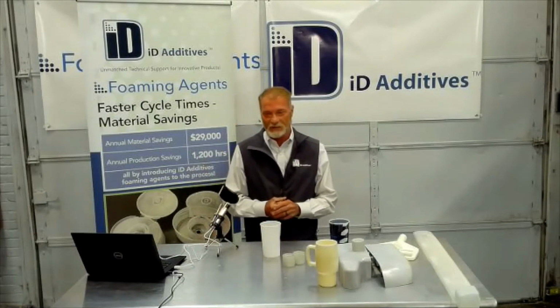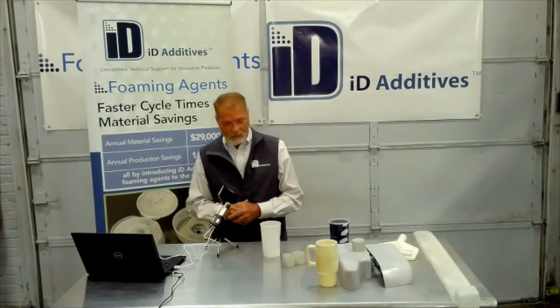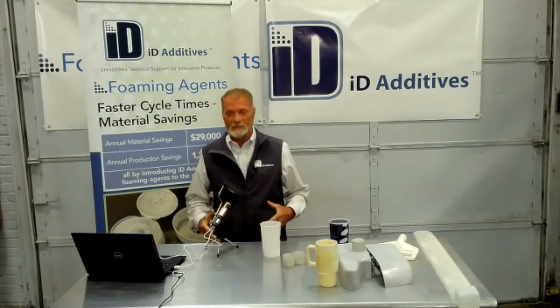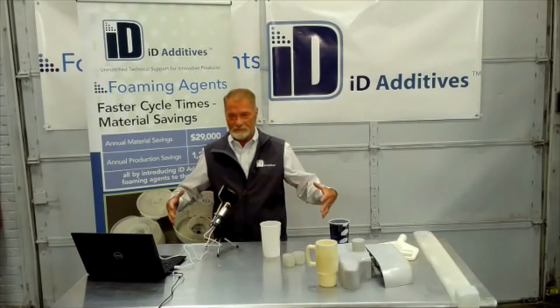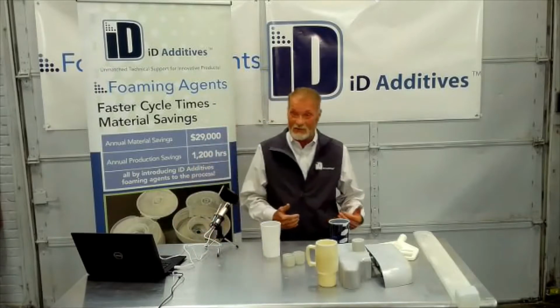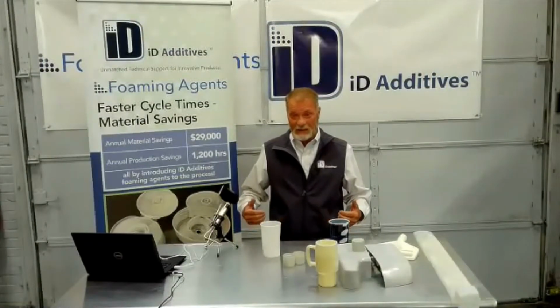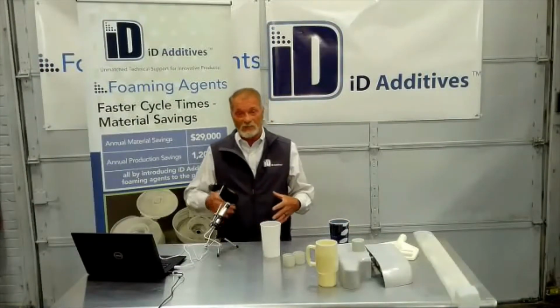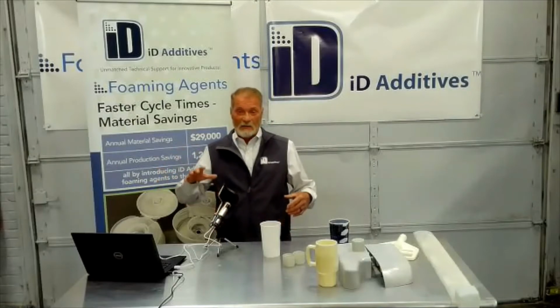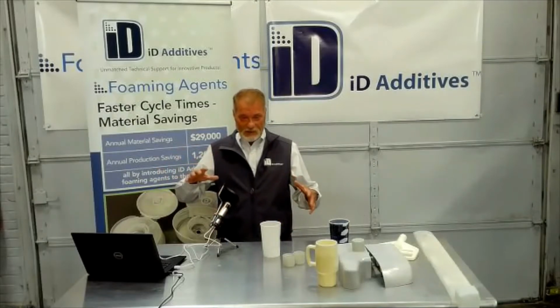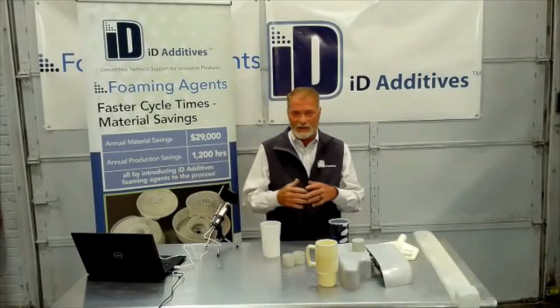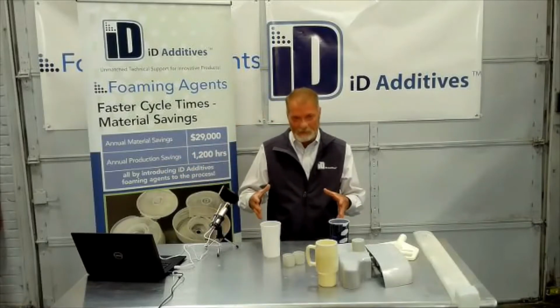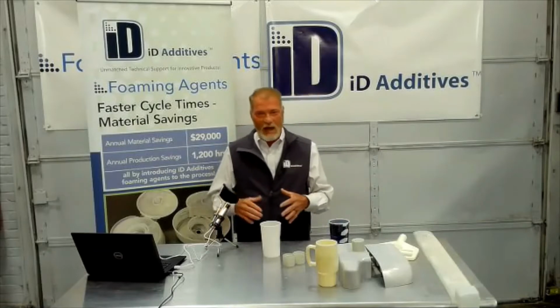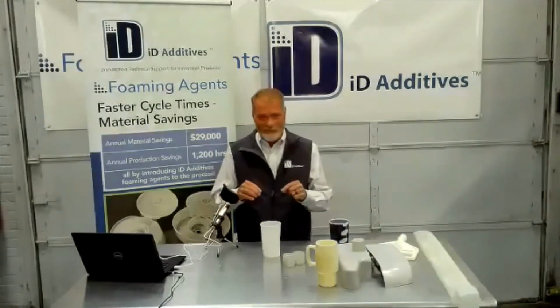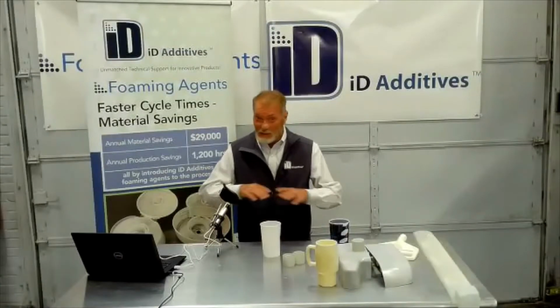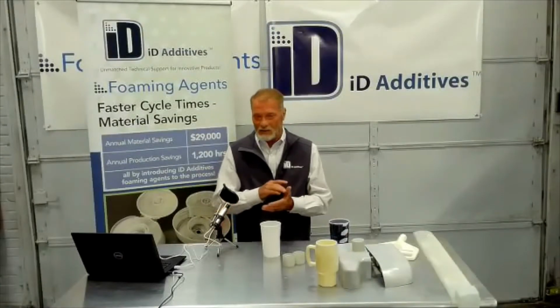Endothermics is for injection molding. When you foam a part, everything's gone off. There are no particles in there that haven't gone off. They've all gone off. We have customers that literally grind up parts and put them in a high aesthetic part. Remember, if you don't change your process and you go into pack and hold pressures like you would normally mold a specific part, you're going to pack the foam. If there are any residuals, which there are very few, if any, you're going to pack them completely out. You're not going to see anything in the wall or on the surface.